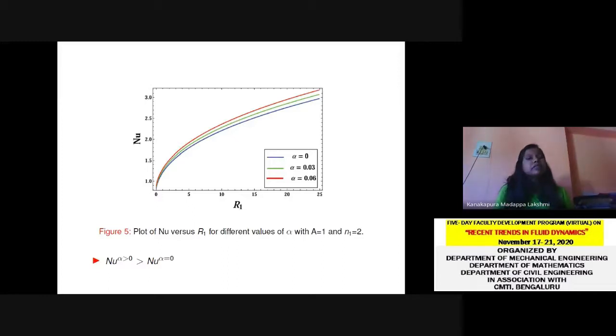Figure 5 is the plot of the Nusselt number for different values of volume fraction alpha, and from the figure it is clear that as the volume fraction increases, the heat transport in the system increases. From this we can conclude that the addition of a dilute concentration of nanoparticles in the system significantly enhances the heat transport in the system.